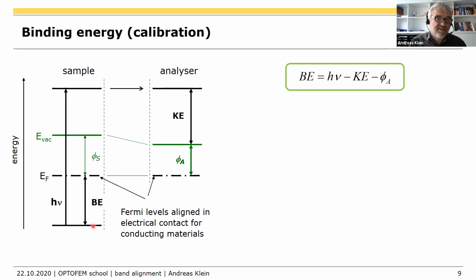This binding energy is now the excitation energy minus the kinetic energy. So the excitation energy is what we know. The kinetic energy is what we measure. And then we have here this quantity, which is the work function of the analyzer. We cannot easily measure it, but we can in principle indirectly measure that, and very accurately. Because what you need to do